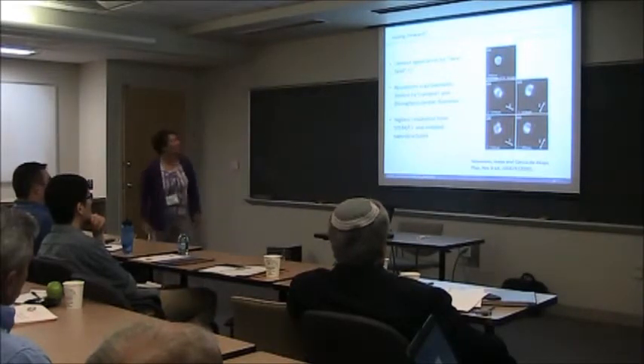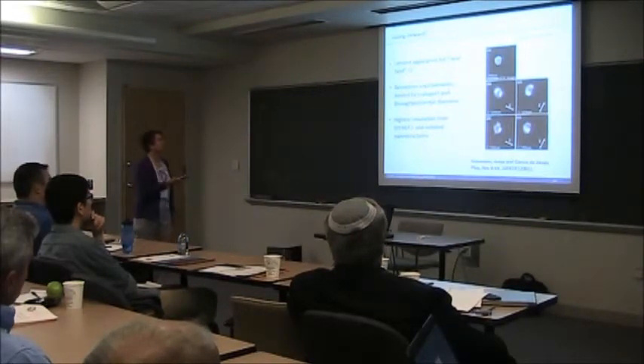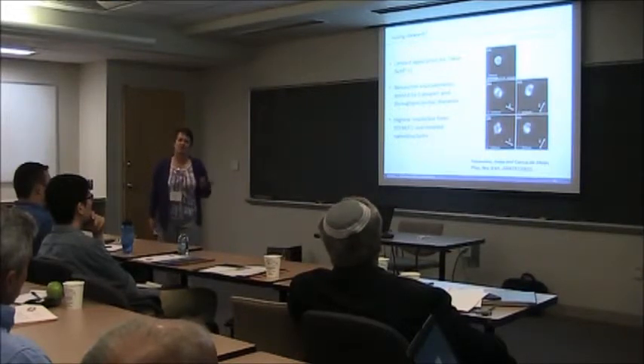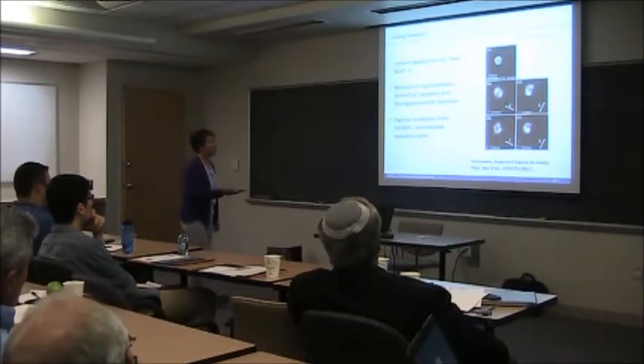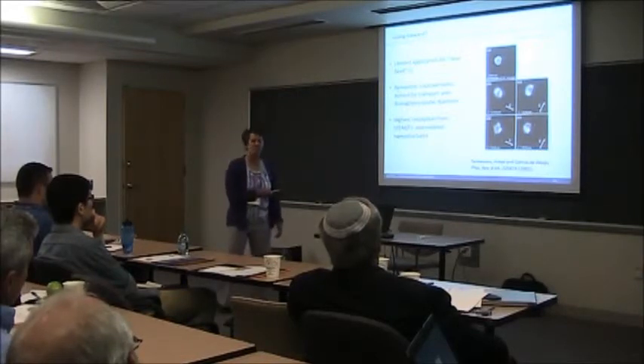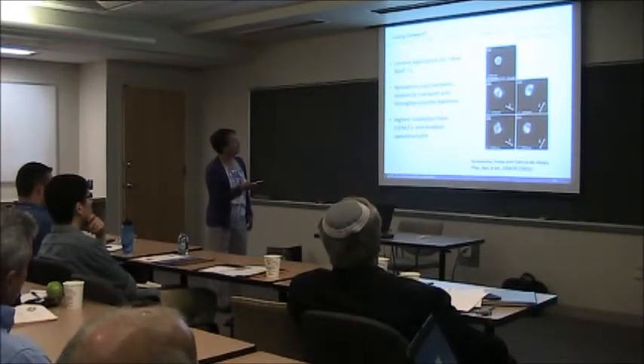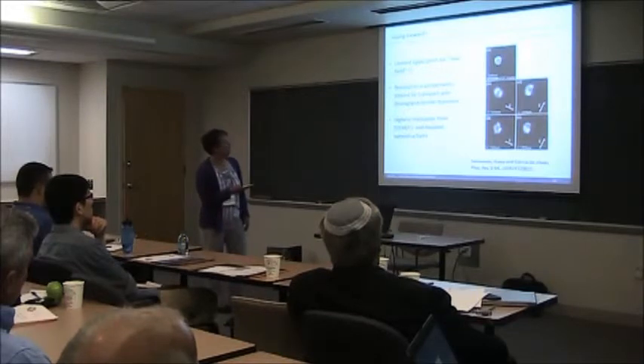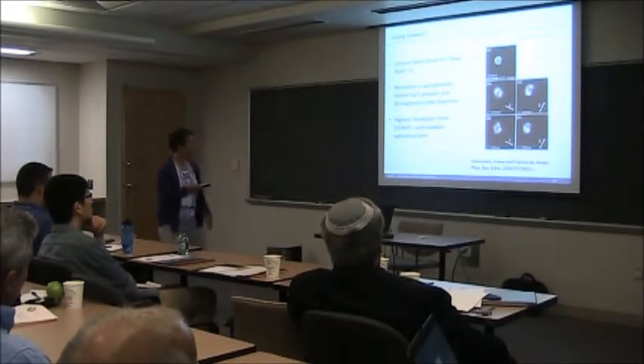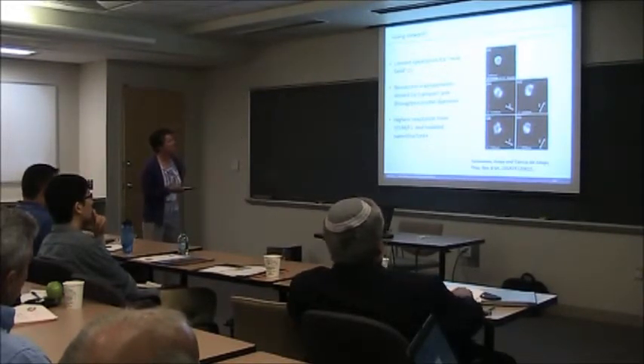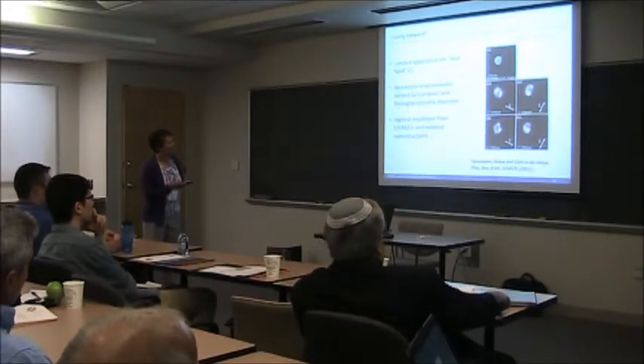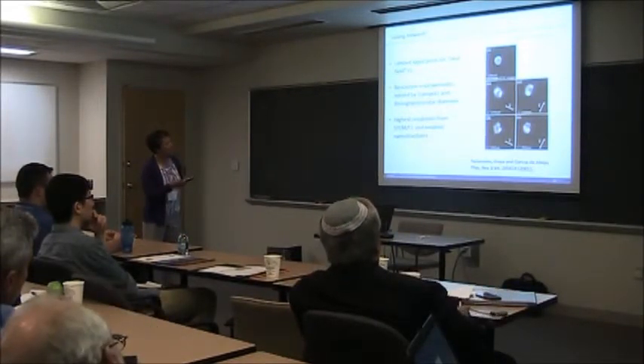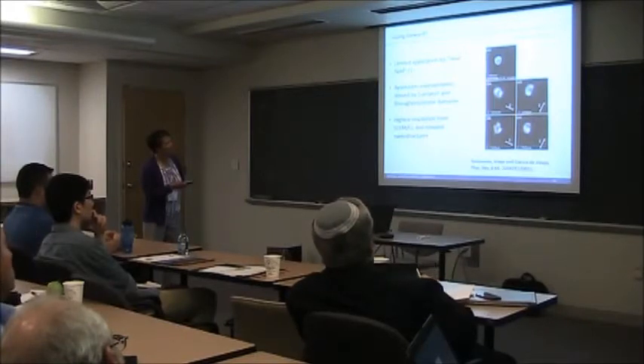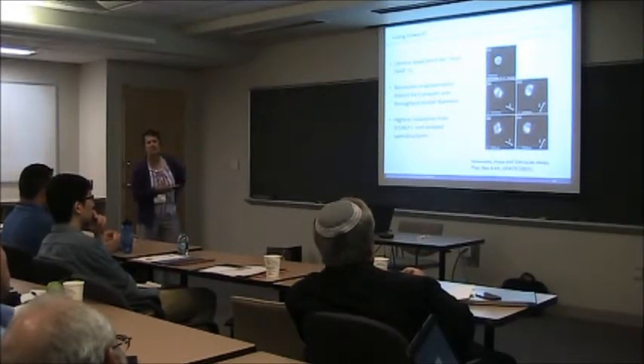So going forward, where do I see this? Well, I think there's very limited application for near-field CL that drove the original papers. Why? Because if you watch what people are doing with STEM now, these are CL images associated with, I think, photon or plasmonic kind of things with silver nanoparticles. But this is 200 nanometers, okay? These are wavelengths, so forget those for a minute. Look at the scale bar of 200 nanometers, and there's the spatially resolved luminescence as they scan the beam.